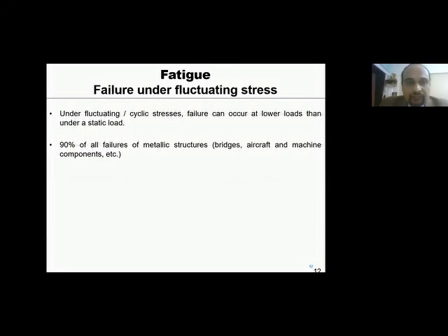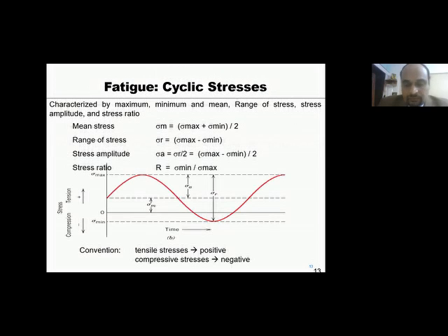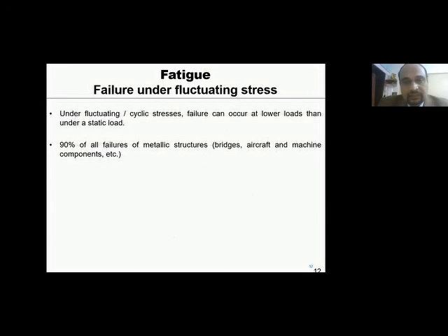Now coming to fatigue failure. Fatigue happens under fluctuating and cyclic stresses. As a matter of fact, the failure can occur at very low loads compared to the static load. If you keep it loading statically versus the part rotating, it can fail at a very low load. That's called fatigue. In the industry, 90% of all failures of metallic structures are fatigue failures. That is what the data says. So mainly the failures that we observe in all industrial applications, aircraft, machining components, etc., the reason is fatigue failure. The root cause could be various, but the reason is fatigue.